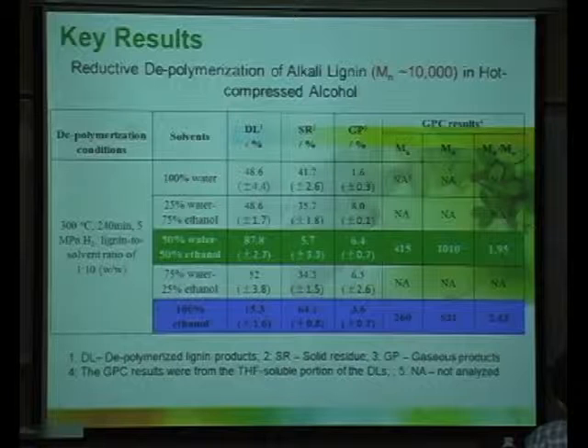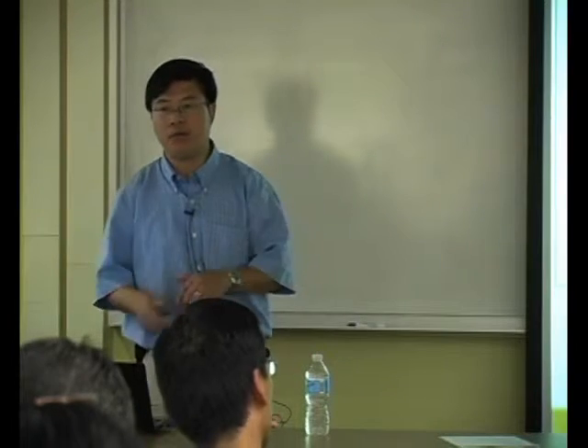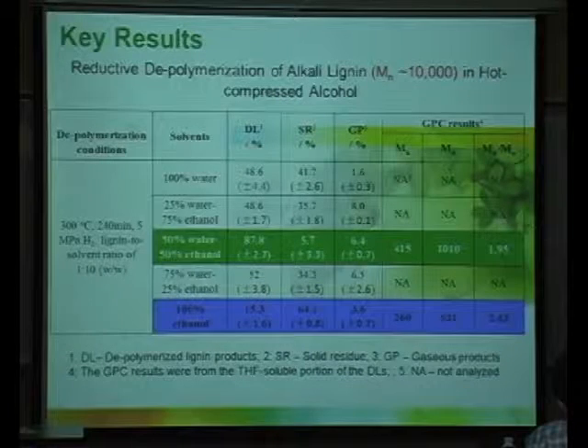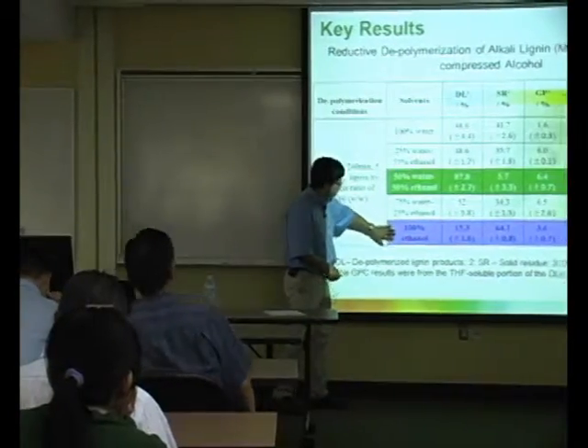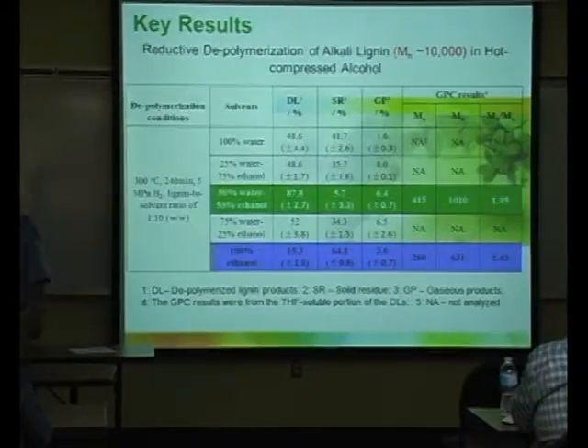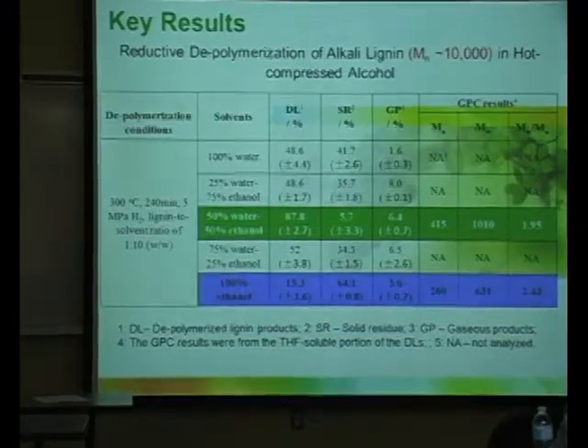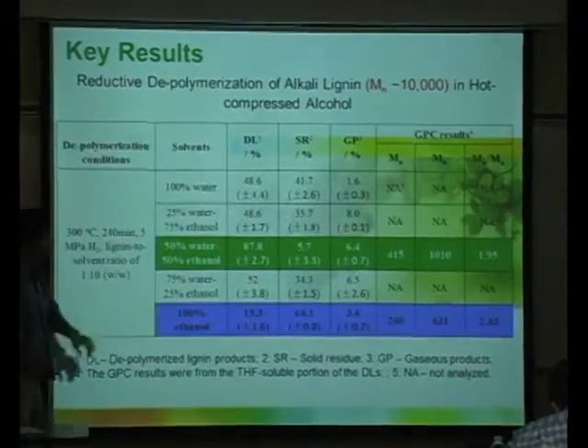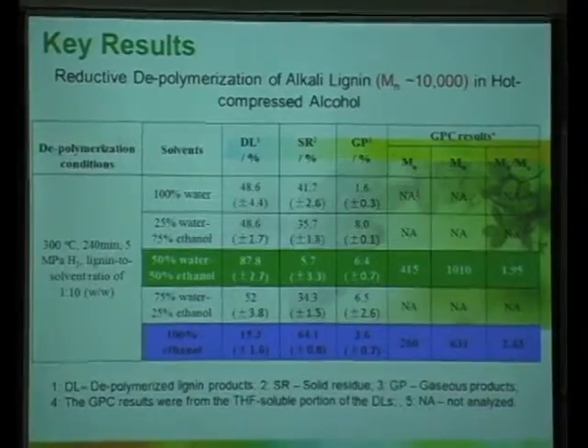Mn for those, NA means they're too large. It's still large polymers, so large oligomers. So it's not detectable in the GPC equipment. But for this system, we can get 415, very low compared to the original lignin. 415, if you look at the monomers, actually it's about a dimer or trimer range. So that's the average. And if you depolymerize in ethanol, even though the yield is low, the molecular weight is even lower, so 260, almost one or two units only. So that's a very, very large depolymerization degree, which makes this product very useful as a biophenol.